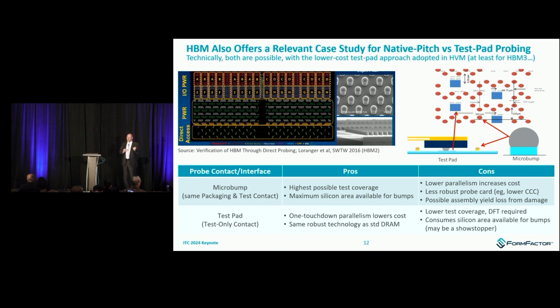You see the micro bumps that the different DRAM stacks, different DRAM die are going to be used to attach to each other over in the SEMs on the right. And so you've got these things, they're about 20, 30 microns in diameter, 55 micron pitch for this HBM2 example. Over on the right, a cartoon of the top-down view of those. So you've got this sea of micro bumps, and then interspersed, you've got these test pads, right? So I've got two choices here. Do I probe the micro bumps, or do I put these test pads in and then use those as the interface for probe, decoupling the packaging contacts from the test contacts? And there's different reasons, there's different choices, as you can see in the table down the bottom, to do both.